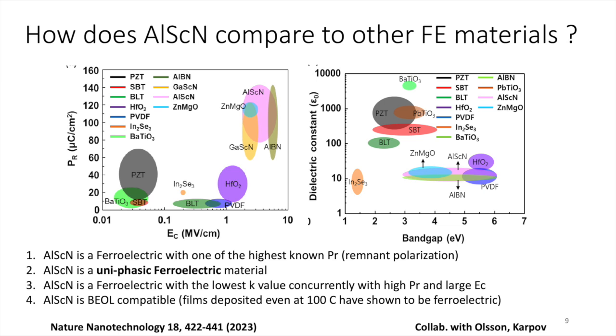But what you can see over here is that we are comparing various ferroelectric materials on the left-hand side graph. And what you can observe is that this aluminum scandium nitride ferroelectric has one of the largest polarizations and coercive fields concurrently. In other words, it's an extremely polar material. It can store a lot of charge in a very stable manner, which is good in many ways. There are also bad things about it. For example, you don't want this high of a coercive field.